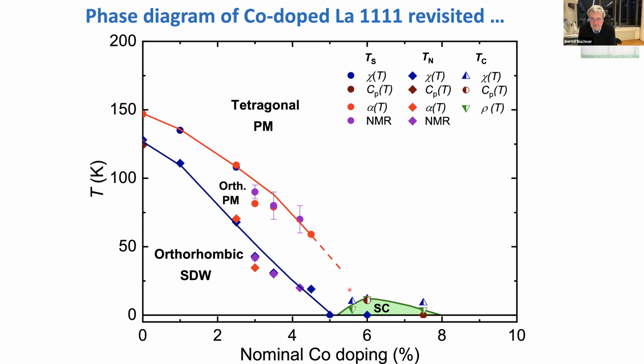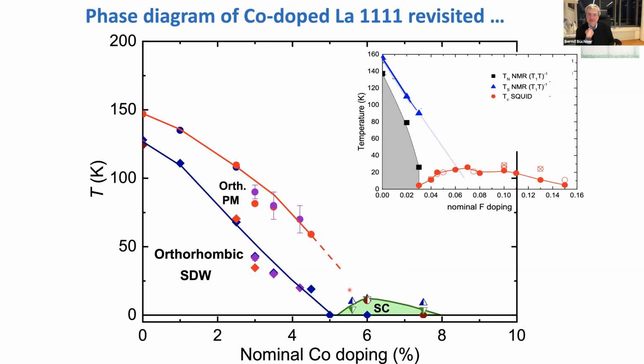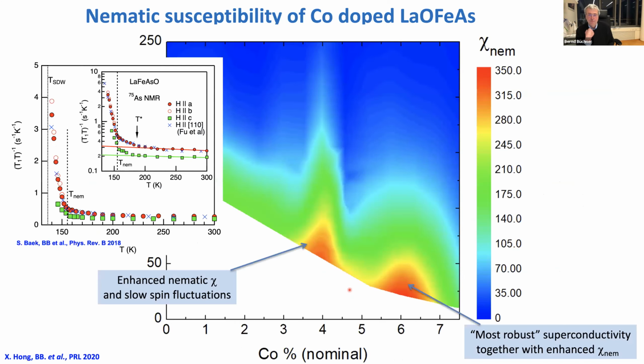Maybe we have to go a little bit further in the analysis of this thermotransport, because there it's not scattering. Typically when people discuss nematic susceptibility, they take this anisotropic scattering as the main mechanism. And I think what we see here is that there is indeed a very subtle response of the Fermi surface as a function of strain. And for me, this looks more like orbitals. That's one story. Then the other story is maybe homework for theoreticians.